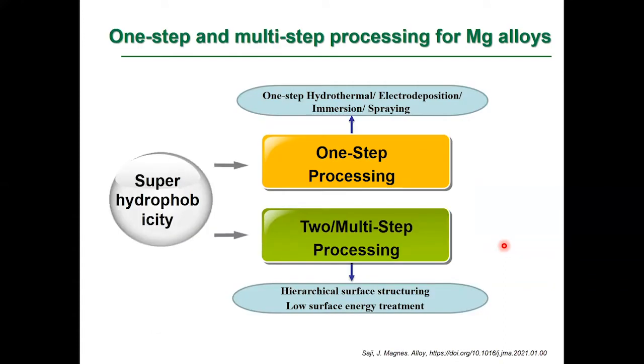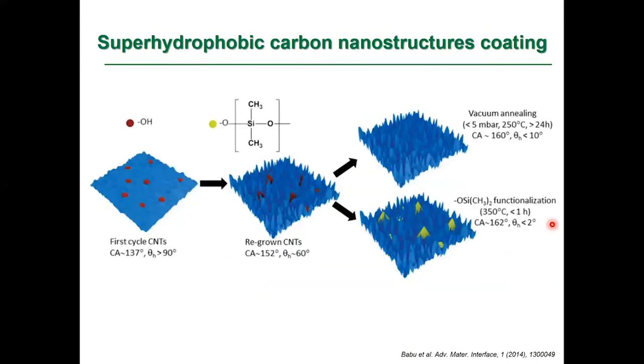These two steps can be achieved in a single step or in a multi-step process. For example, for magnesium alloys, we can achieve superhydrophobicity by a one-step hydrothermal process, or one-step electrodeposition process, or one-step spraying, or it can be in different steps. For example, first hierarchical surface structuring, then maybe other steps, then low surface energy modification, and multiple steps depending upon the applications. So different processes are used.